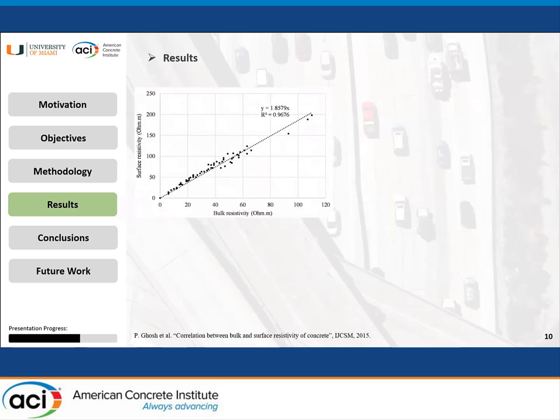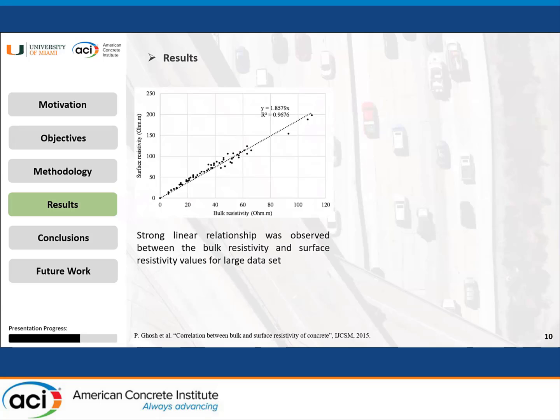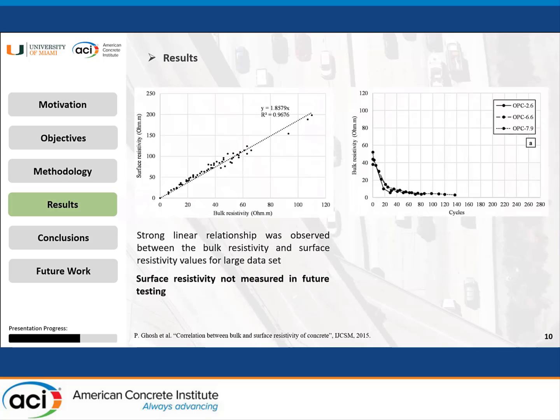In this slide, on the left side, you see the surface resistivity values, which were measured for a large amount of samples versus the bulk resistivity, and it's obvious that you're experiencing a strong linear relationship between these two values, and that's why the surface resistivity was not measured in the continuation of this study. On the right side, you can see the bulk resistivity values for our control mixes, which were just having OPC with various amounts of air as the cycles initiated. So you see that as the samples were submerged into the de-icing salt and the cycle started, the bulk resistivity has decreased, and this keeps happening as the exposure duration increases.